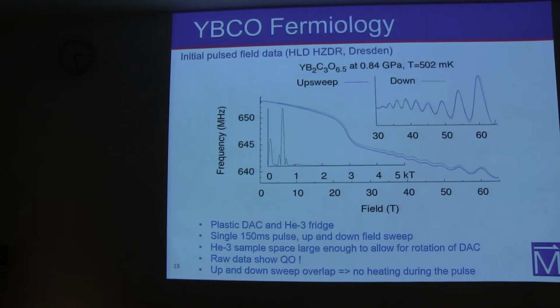So for our results, those are our first data that we collected in pulsed magnetic field in Dresden, with a 70 Tesla magnet, and that was done at 8 kilobar and helium-3 temperatures. What we see here is I plot the TDO frequency that we measure as a function of magnetic field, so up to 65 Tesla here. And you see two curves here, one purple and one green. One is for the upsweep of the pulse, and one is for the downsweep of the pulse. And one thing that's really important for us is that those two curves overlap perfectly. We see that by those oscillations here that have the same amplitude.